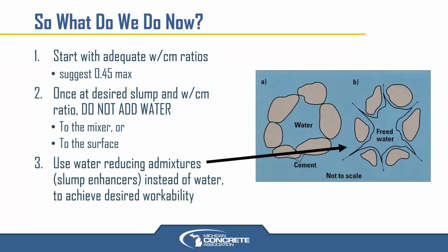Instead, use higher amounts of water reducers. Again, use more water reducer, a different type, or up your dosage. Batch it at a 0.43 and a 4-inch slump, whatever the contractor wants or is allowed in the spec. Leave a little bit of room maybe to add some water, but hopefully they don't need to. But try to achieve what you need with chemicals.